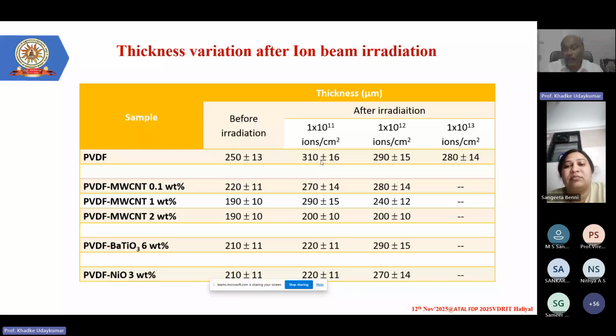Later, it has been settled. Continuously, we are bombarding it with a different, higher fluence. So again, it has decreased to 290 micron, and with a further increase in the fluence, it has settled back to 280, and later it has not changed. It has not come back to 250. This is just to show that after ion beam implantation, bulging of the film has taken place.